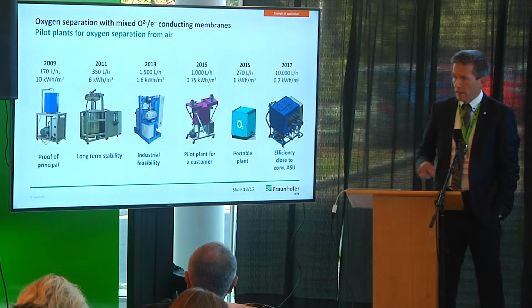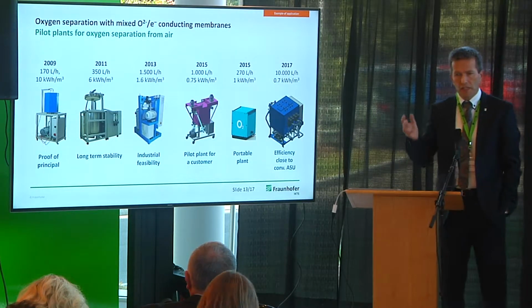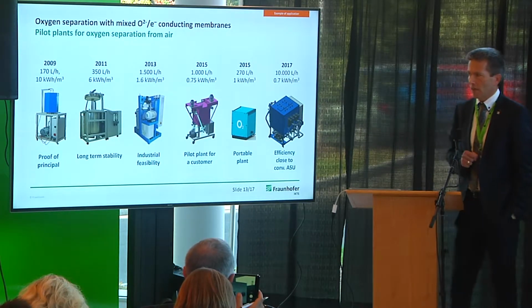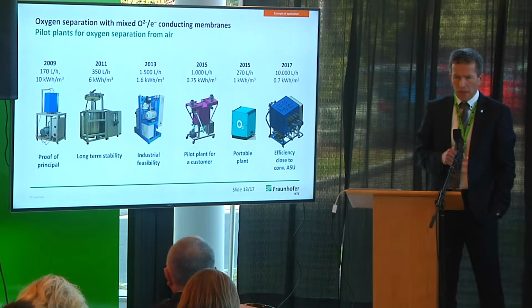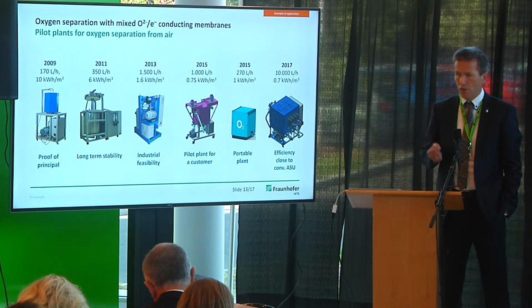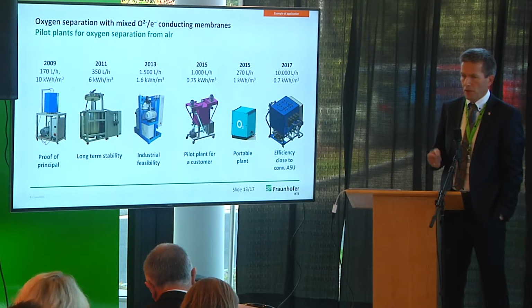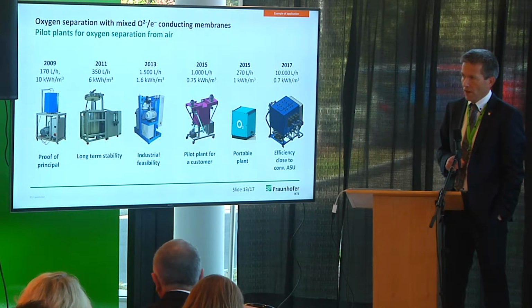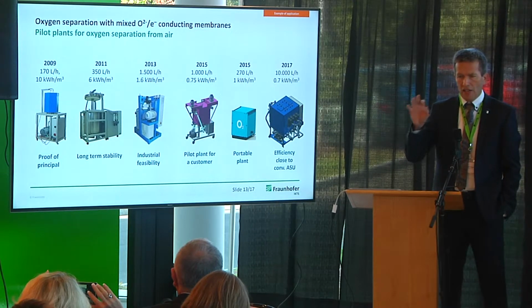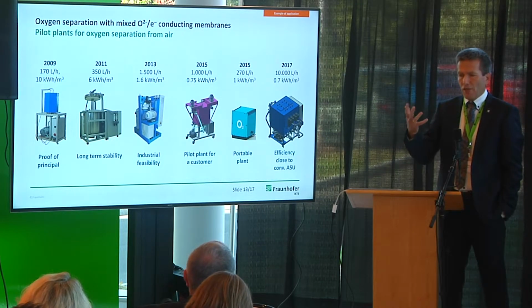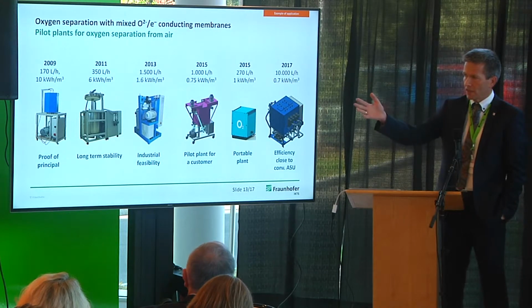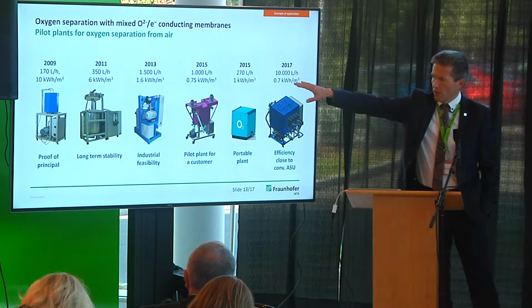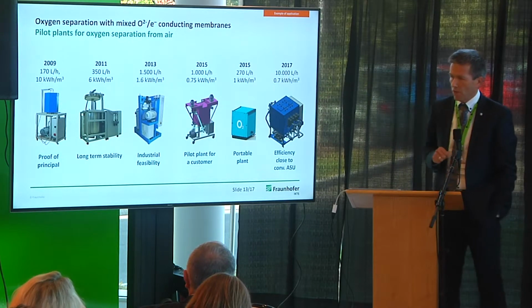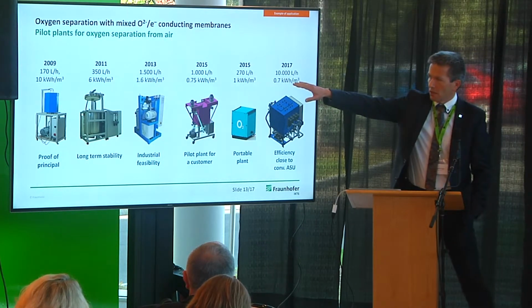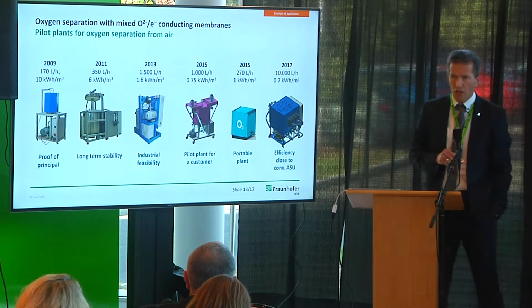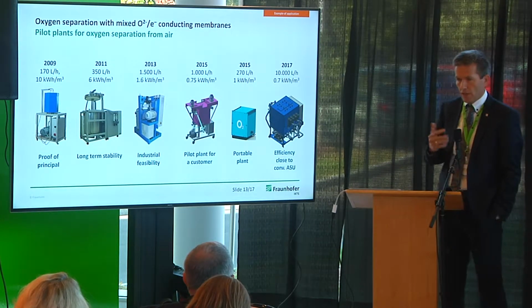Well, next example is in oxygen separation with the mixed ion electron conducting membranes. Here we succeeded in the development of high performance membranes, perovskite membranes with very high oxygen flux, and then we focused on the energy consumption, on efficiency of the membrane process. And you see here that we were able to reduce the energy consumption per cubic meter of oxygen, and with 0.7 kilowatt hour per cubic meter, we are close to the efficiency of a large conventional air separation unit.